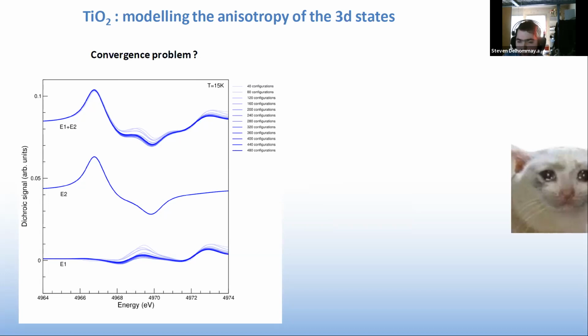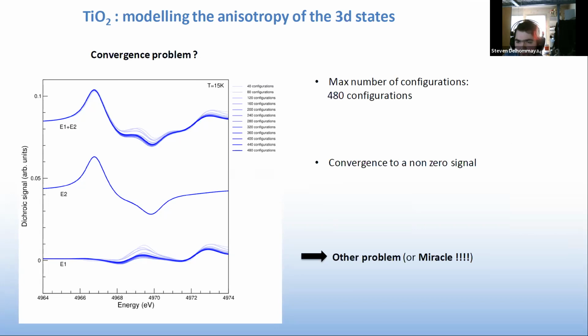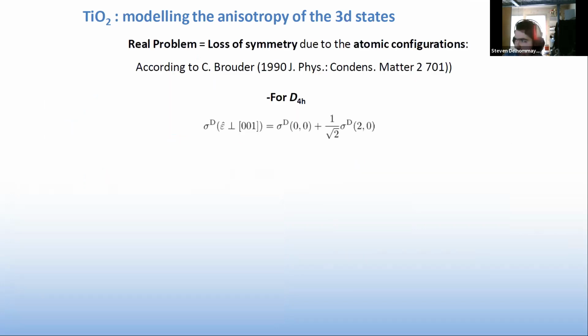And so we have another problem, and it turns out that this problem, in fact, is a symmetry problem. I will go very fast on this part, and maybe you can ask me questions to explain. But according to Christian Brouder, here's what the cross-section should look like in our specific experimental setup. And you see that when epsilon varies in this plane, it is always the same thing. So in fact, the E1 contribution must be zero here.